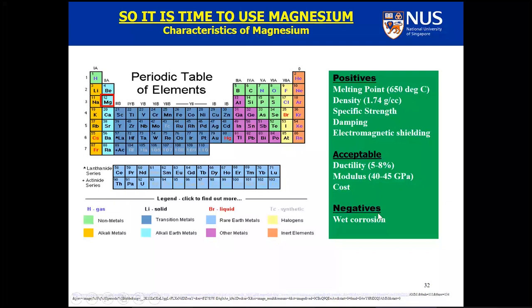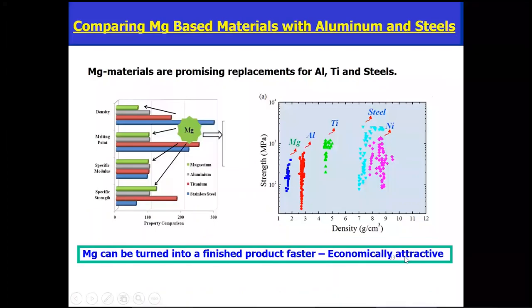So if you have to use magnesium in a wet environment, you ensure that you coat it the same way you coat steels with either zinc or some coating. You have to use coated magnesium. To compare magnesium with the workhorses of the metallic elements like aluminum, titanium, and steels, you will see in the picture on your left-hand side, it has the lowest density, it has the lowest melting point, it has a similar elastic modulus or specific modulus when you compare with these elements, and its specific strength is only next to titanium. But titanium is 5 times more expensive than magnesium.